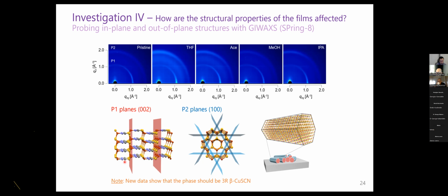So the long length of the crystals are aligned. The longitudinal directions of the crystals are aligned with the plane of the substrate. So they are lying like long needles on the plane of the substrates, basically.